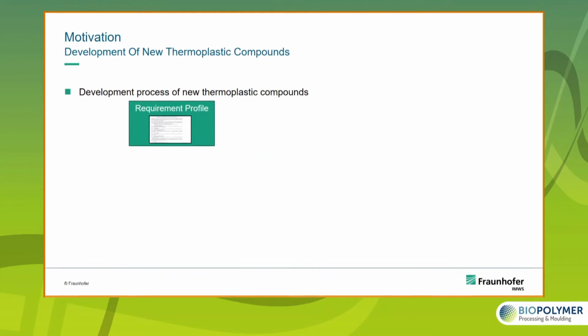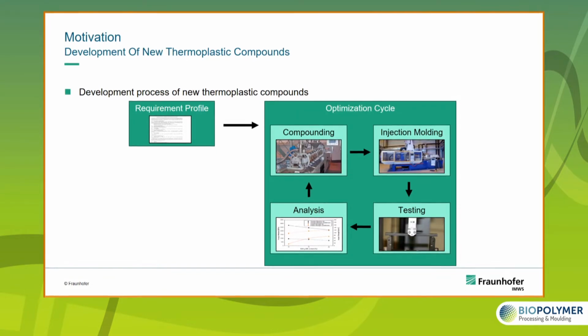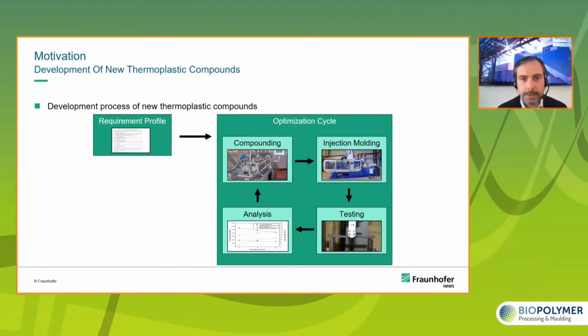So what are the tasks if you want to design or develop new polymers, new compounds? At the beginning, you always have a requirement profile of your material where the needed mechanical properties, processing properties, and so on are listed. And this gives the start for the optimization cycle you will enter. So first step is compounding, real mixing of new materials. The second step is production of test specimen, in most cases by injection molding. And later on, you will do the testing, for example, tensile testing, and those tests are then analyzed. And if the requirements are met with the test results, you are done and you can leave this optimization cycle. If not, then you have to repeat the cycle until you reach your required properties.